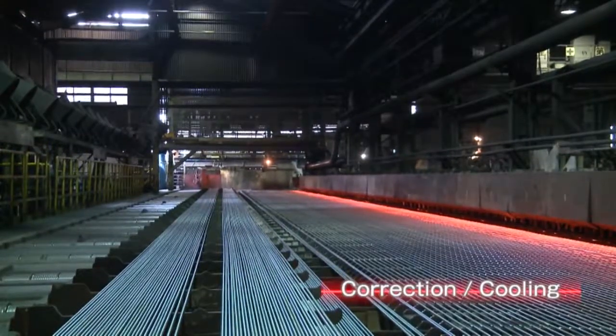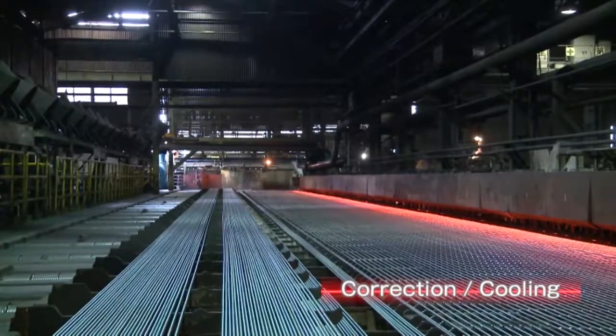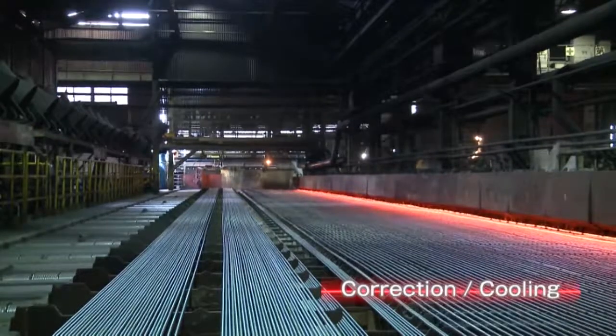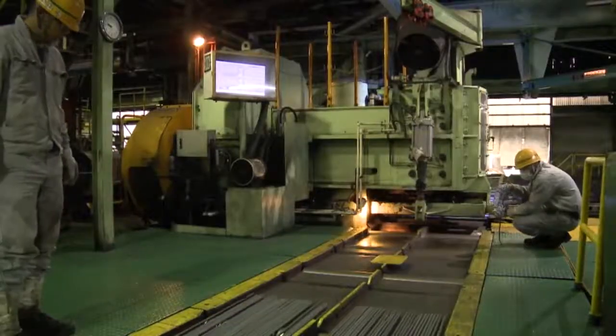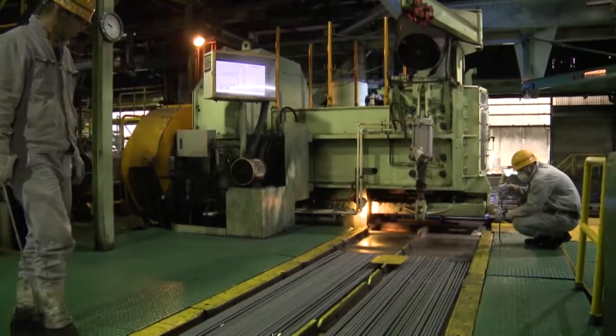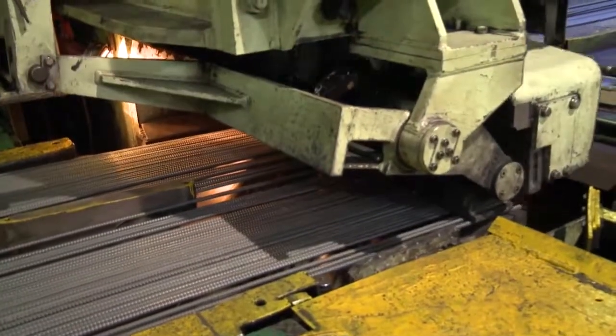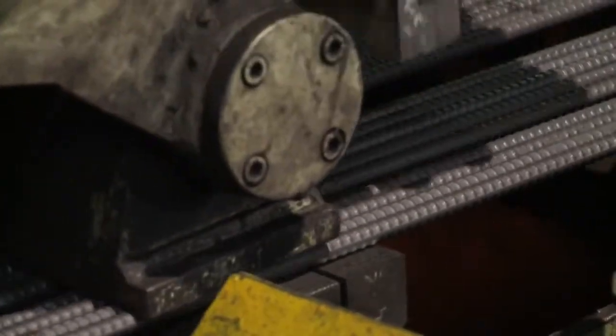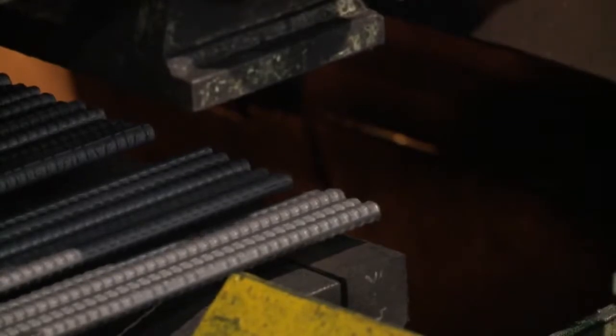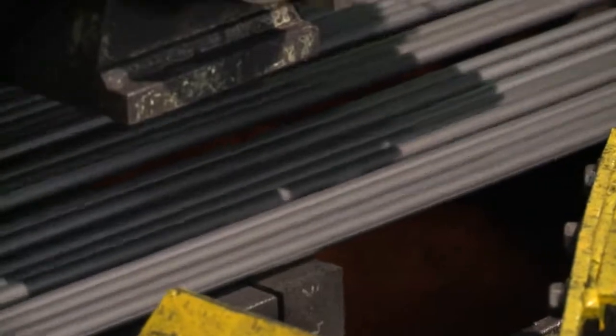Now the shaped iron rods are cooled on the cooling bed. The cooled rods are sent to the finishing line. An external inspection is conducted here, and they are cut to regulation length. The cutting machine uses the downcut method. The cutter with a 1,300mm blade prevents overlapped cuts and is also designed to prevent bending during cutting caused by pressing and tilting equipment.